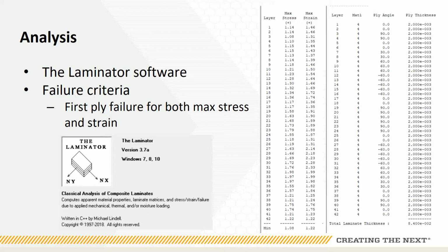The Laminator software takes the stress and strain in each lamina and divides it by the max value. The numbers are then outputted as shown. If any value is below 1, that ply has failed, and therefore the entire laminate failed. As seen, the minimum values for stress and strain for this case are 1.08 and 1.22, so the laminate has passed.